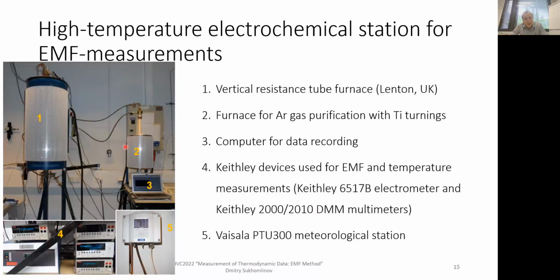Then this furnace number 2 is a very important second furnace, which is employed for argon gas purification. We fill it up with titanium turnings, and argon gas, while passing through heated titanium turnings, loses a lot of, well, a lot, maybe not the correct word. Usually quality of argon gas is pretty good, and oxygen concentration in argon is just 1 or a bit more, just a few ppm. But titanium turnings remove that as well.